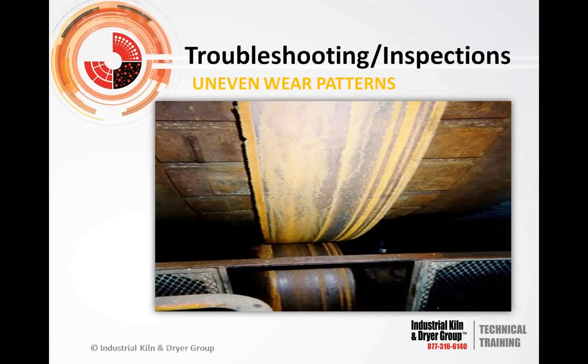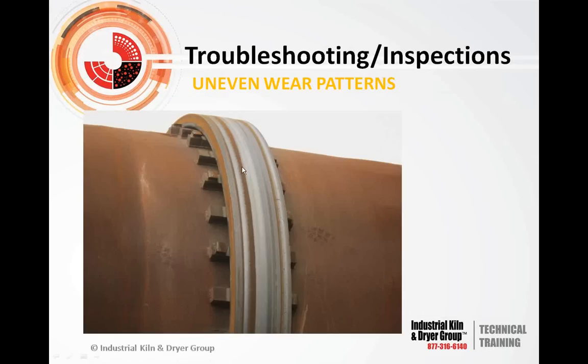Another type of wear that you're going to see out there from time to time is an uneven wear. So you're seeing bands of wear around the tires and rollers, and this is typically, in most cases that I've been around, a situation where it's a contamination issue. For example, I see a lot of times where this roller will be running in product. The product has grease mixed in with it, metal flakes, all kinds of different abrasive materials. And as the roller runs into it, it picks it up, and it actually starts to wear into the surfaces with an uneven wear pattern. And this is another example of an uneven wear pattern where you're not getting full contact across the face of the tire.